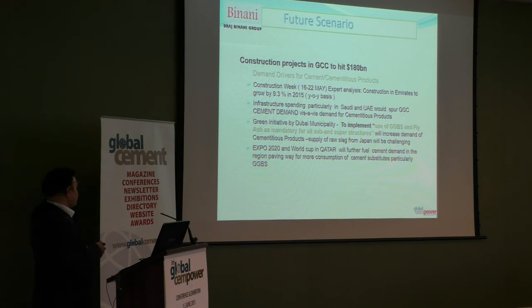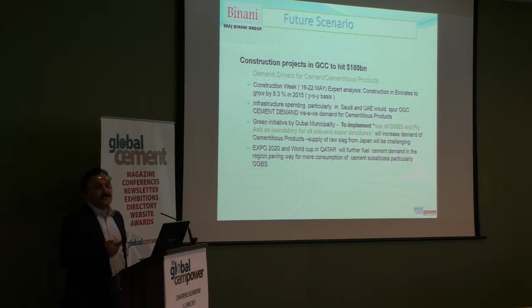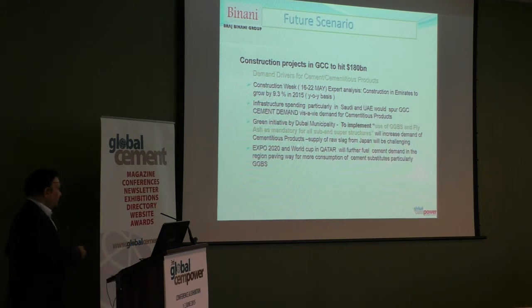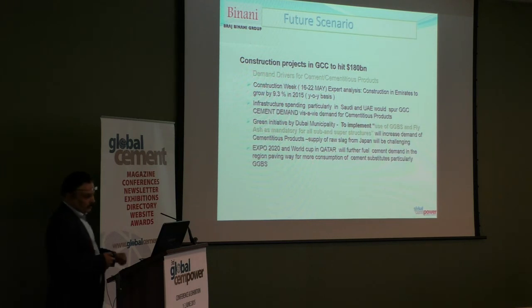So what's the future scenario? Now a lot of changes are happening. Apart from the growth in construction, recently Dubai municipality has announced use of GGBS, I mean ground slag, and fly ash, as mandatory in all substructures and superstructures. That would mean more use and more consumption of slag. So if you have this kind of scenario, we expect that Dubai alone will consume at least 500,000 tons more slag. Plus, you also have events like Expo, and then you have World Cup in Qatar. These are the events which are further going to fuel growth of cement as well as cementitious materials in the region.